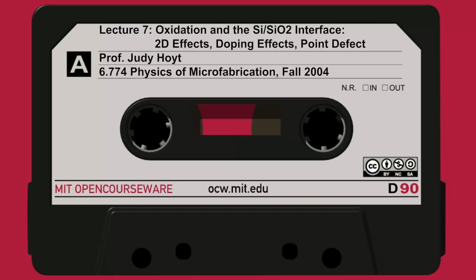If you grew an oxide in dry oxygen at 800 and you didn't anneal it, you might have on 111 silicon about 6 times 10 to the 11th for your QF per square centimeter. If you anneal it in nitrogen or argon at 800, you can get it down to about 1 times 10 to the 11th on 111 silicon. On 100, all the numbers will be about 3 times lower. If you anneal at a higher temperature, you'll also come down. So the whole idea is to anneal in an inert ambient at a relatively high temperature right after your oxidation.